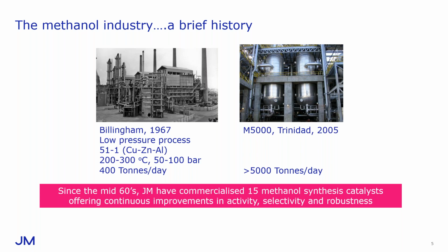Since that time, there have been improvements in both catalyst performance and process design, such that world-scale plants now commonly exceed capacities of 5,000 tons per day. Now, since the 1960s, we have introduced a sequence of ever more active and physically robust catalysts, and we are now on our 15th iteration. However, the single biggest improvement that we've made to the performance of the catalyst over those 50 or so years is that which is associated with the development of 51-102.